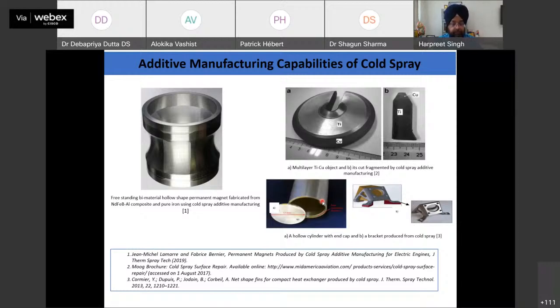have tried. Now you can see, this is a freestanding bi-material hollow shaped permanent magnet fabricated from this one. So this is some shape which has been prepared by cold spray. Similarly, we can have this also, multi-layered titanium. So see, one thing is that here even materials with different chemistries can be worked upon. Okay, that's another interesting feature of this, because in the earlier processes you will face some problems.